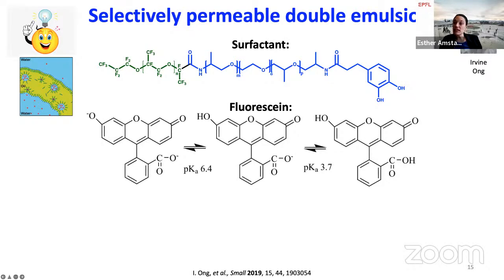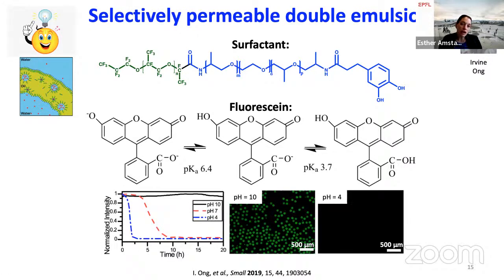First question was, does this functionality that we introduced actually already allow us to suppress this fluorescence? And to test this, again, we used fluorescein in the core. We stabilized the emulsions with these surfactants without ionically cross-linking them, and we looked at the fluorescence. And what we saw is that in this case, the transport is very strongly dependent on the pH.